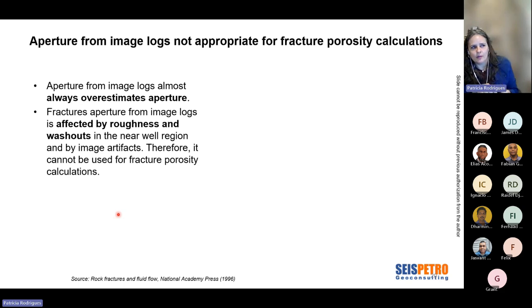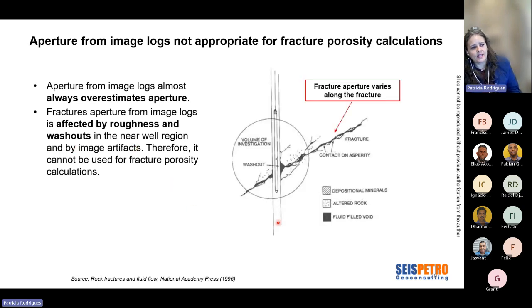It's usually not appropriate when you're trying to do fracture porosity calculations. It tends to overestimate the aperture of the fractures because it is affected by roughness and washouts near the wellbore region. So it has image artifacts. So basically what is happening here is that what we're seeing is just when the fracture crosses the borehole.